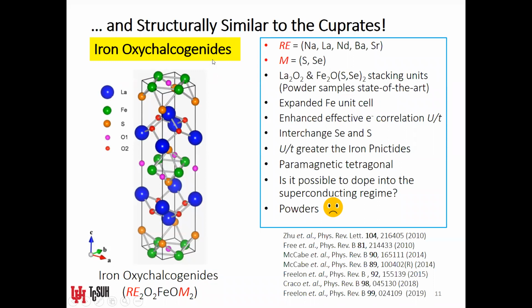However, in these materials, in these iron oxychalcogenides, there is an oxygen layer here, and I think that color is pink. I'm a little colorblind, but there's an oxygen layer that sits in the center of the iron plaquettes. What this oxygen layer does is, so it's not quite the same iron layer as the pnictides. It has this oxygen layer in the center of the iron plaquette. What that does is it expands the iron unit cell. The effect of expanding the unit cell is really to increase the effective correlation that we mentioned back a few slides ago. And that leads you to a compound that is certainly more strongly correlated, okay, than the pnictides.